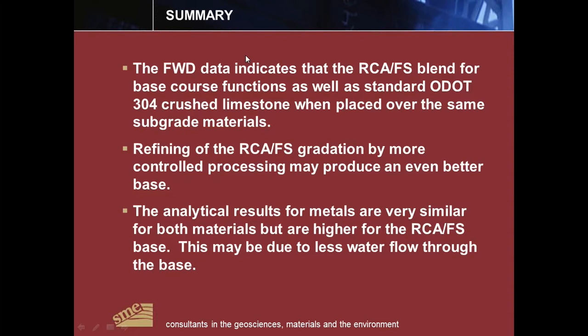So in summary, falling weight deflectometer data indicates that the recycled concrete aggregate foundry sand blend for the base course functions as well, or maybe even slightly better than the standard ODOT 304 crushed limestone when placed over the same subgrade materials. Refining of the recycled concrete foundry sand gradation by more controlled processing, by better crushing and blending methods, may produce an even better base material with further study.